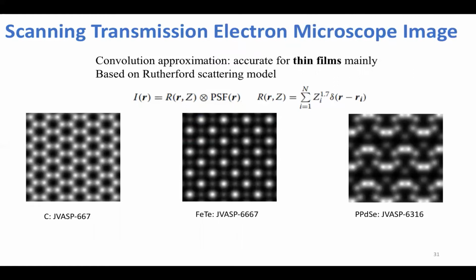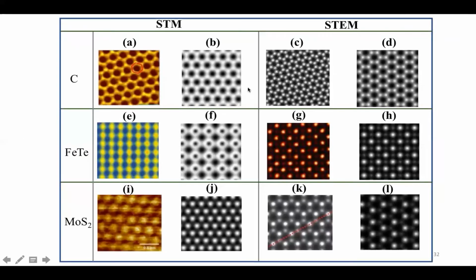For general materials, we'd use multi-slice simulation, which can capture phonons and other contributions, but for 2D materials this approximation should work well. We actually see that in the examples comparing to experiments, such as graphene, iron telluride, and molybdenum disulfide. In the STM and STEM figures, the first and third columns are experimental and the second and fourth columns are simulated images. They compare quite well.